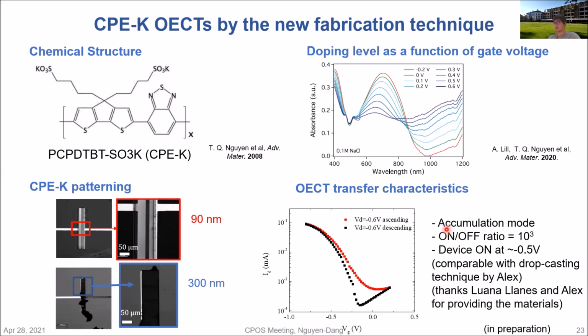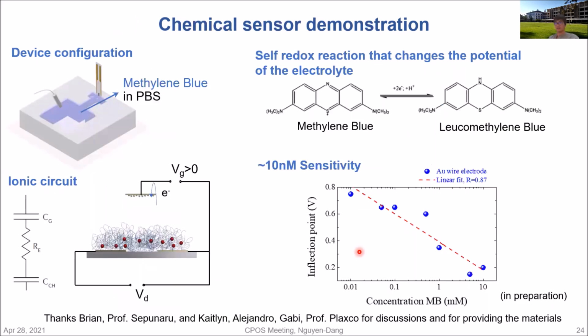So we show that it works in accumulation mode. It's a different mode than PEDOT:PSS, with a high on-off ratio and the device on at low voltage. So basically, it works so well, and that shows that the new fabrication technique can work with different materials other than PEDOT:PSS.